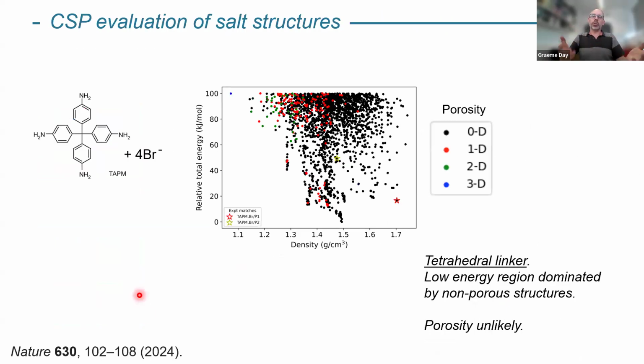Okay. So here's one example of the combinations we tried. Here's the CSP landscape. And I'm color coding things now by porosity calculated for those structures. And what you see on this landscape is, well, it doesn't look like it's worked. Most of the low energy structures here are 0D porosity, which means there's no useful porosity in those structures. And that starred structure here is what you get when you grow this crystal in the lab of this combination of this cation and bromides. Okay. So the predictions have told us that this one wouldn't have worked.